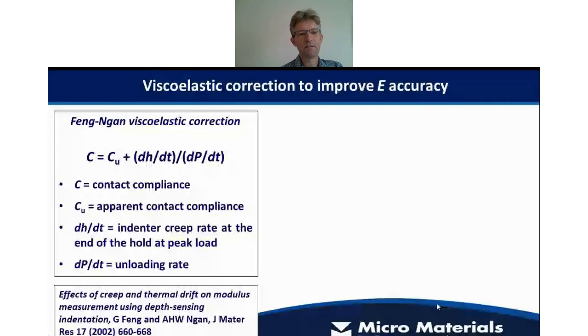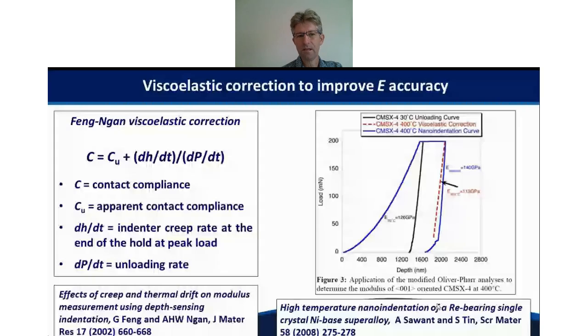So one of the things that we've done, for example, is take a viscoelastic correction originally designed by Feng and Ngan for room temperature tests. As it's shown mathematically there, it's in terms of compliance, not stiffness. And what we can see is that this type of correction allows us to effectively correct from the unloading stiffness that we see with this anelastic deformation occurring within it, to get back to what the real stiffness would be without that anelastic or viscoelastic deformation.